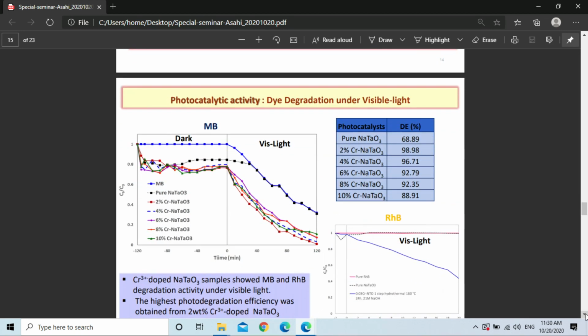We tested the photocatalytic activity for degradation of methylene blue, and from this result, the sample doped with chromium has higher activity for degradation of organic dye compared to pure sodium tantalate under visible light. And we also picked the best sample to test degradation of rhodamine B, because rhodamine B is stronger for decomposition than methylene blue, and we also can see that the doped sample shows higher activity compared to pure sodium tantalate without doping under visible light.